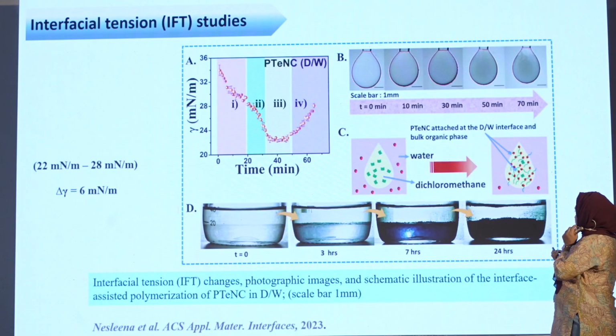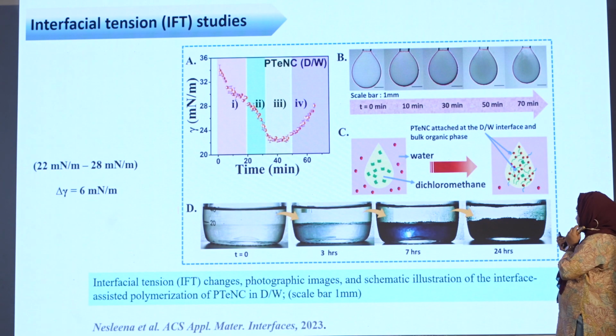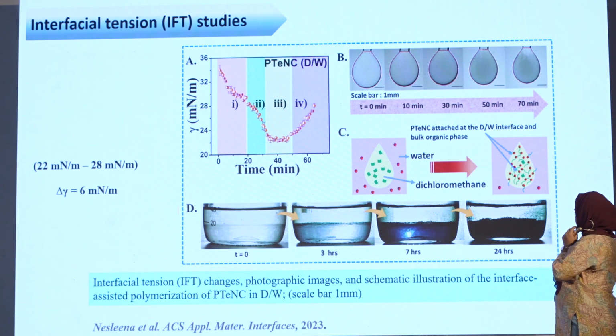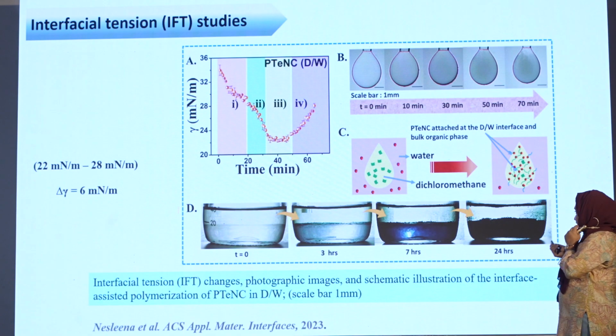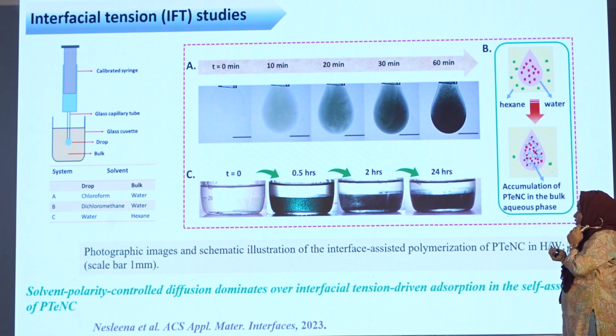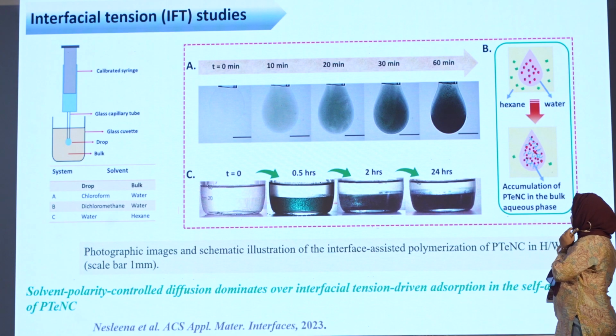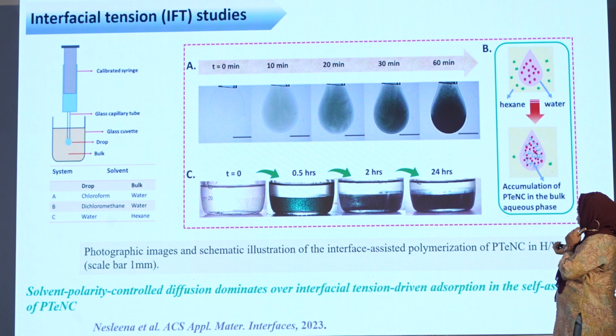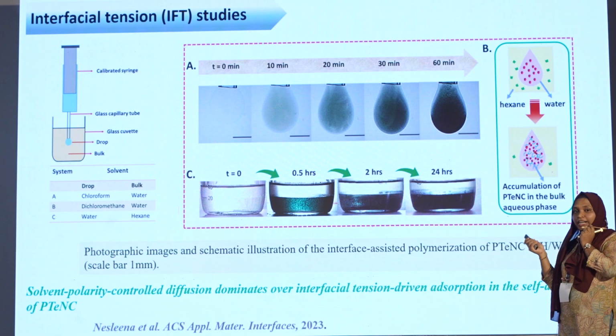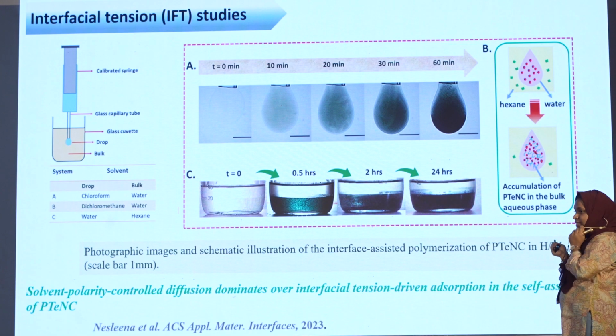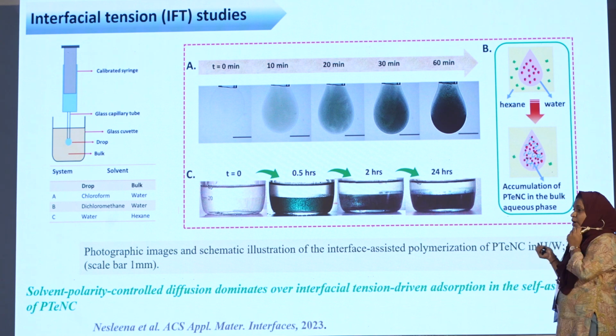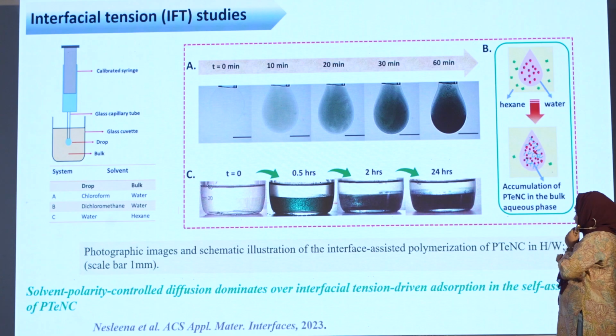This is for the DCM-water system, where an initial stabilization indicating interface confinement, and then a gradual increase in interfacial tension indicating bulk movement was obtained, and the corresponding optical images captured during the reaction are also given. But in the case of the hexane-water system, since there is a meager difference in refractive index between water and hexane, there was a practical difficulty in checking the IFT. However, we observed from the pendant drop studies that only bulk aqueous confinement is there for the hexane-water system. Here, solvent polarity-controlled diffusion dominates over interfacial tension-driven adsorption in the self-assembly process.